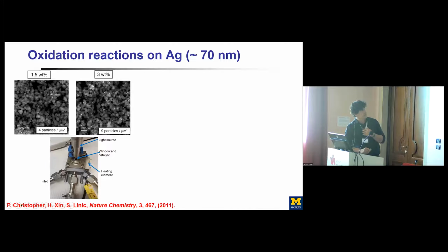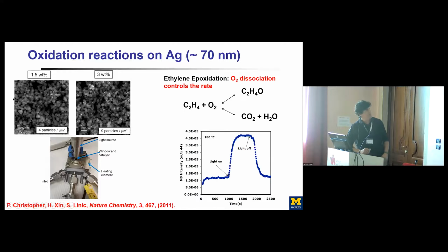We pack this catalyst into a reactor. We have a light that we can funnel into the reactor, and we have an inlet. We're bringing in a stream of ethylene and oxygen. We're going to follow the oxidation of ethylene as a probe reaction, and we're monitoring what's coming out of this system. And these are basically the first results that we obtained. Here you see a mass spec signal of ethylene coming in. As you turn the light on, you see instantaneous oxidation. If I send an inert gas pulse through this system, I'd get exactly the same spectrum, so there's no real time delay that we can measure.